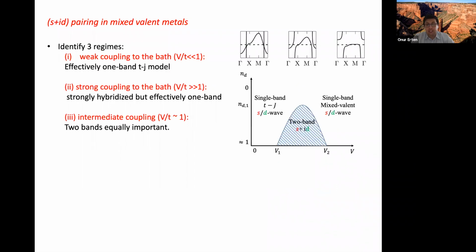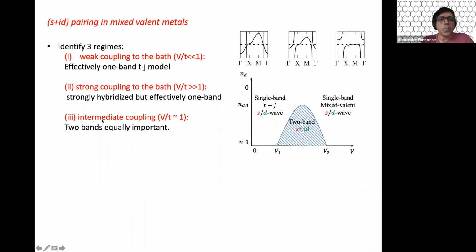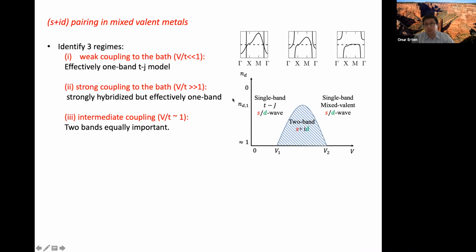And mainly the three regimes here are when this T, if your strongly interacting band is flat, completely flat, like heavy fermions, then you are always in this strong coupling to the bath regime, which gives you effectively a single band picture of strongly hybridized quasi-particles.